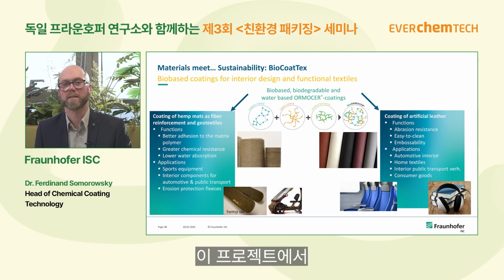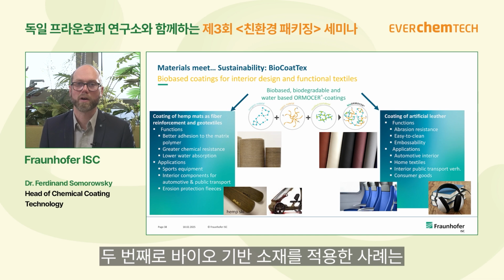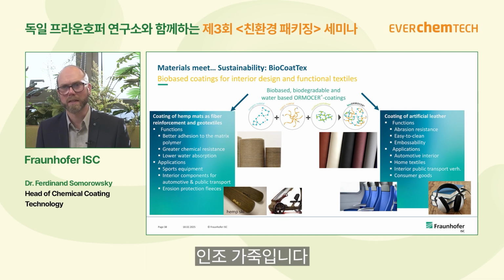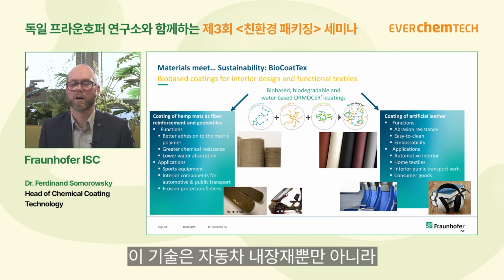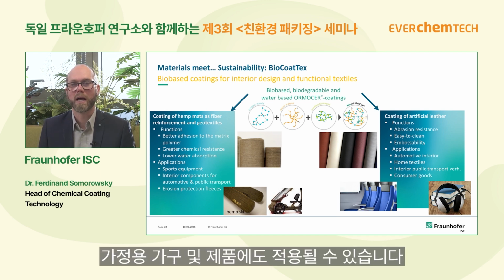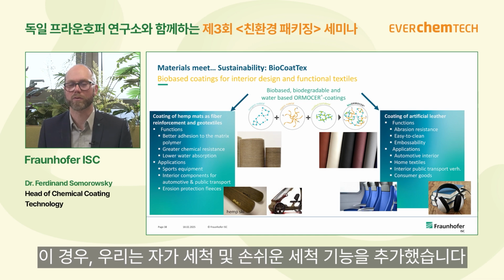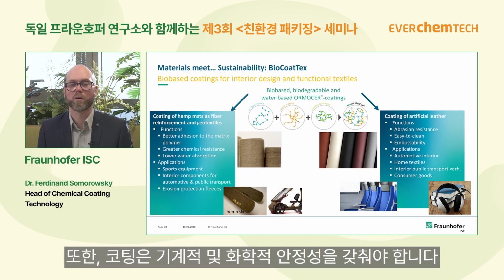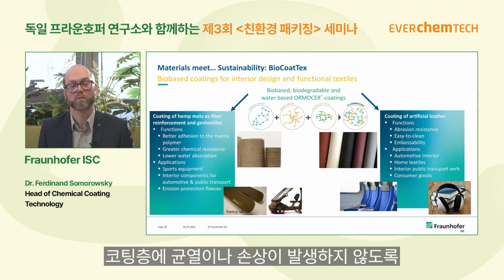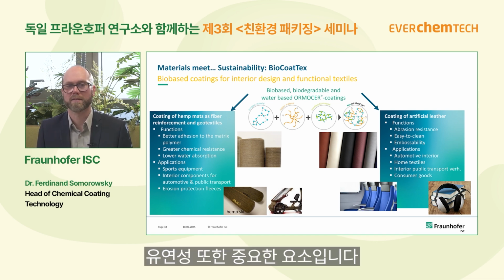The second use case in this project, where we also use bio-based materials, is the application on artificial leather for automotive but also for home applications. Here we integrated additional self-cleaning and easy-to-clean properties, and of course the coating has to be mechanically and chemically stable. It should also be very flexible, so that no cracks form in the coating layer.